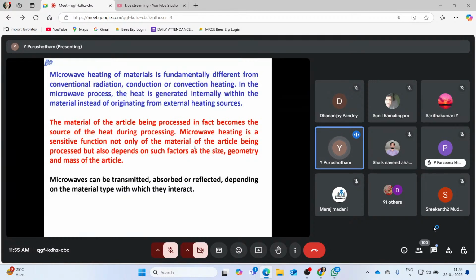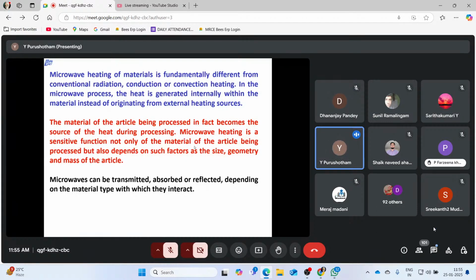Why is this fundamentally different from conventional heating? In conventional heating, for example resistive heating, you have to heat up to the target temperature, and that will take time to reach. Till that time, whatever material you have placed in the furnace for sintering will be exposed. After reaching the set value, you have to maintain it for a certain period, certain hours. Then you have to reduce it, and it will take time to come to room temperature. So from loading to unloading, you are exposing your material through the conventional resistive heating.